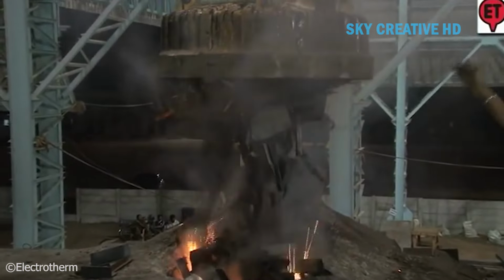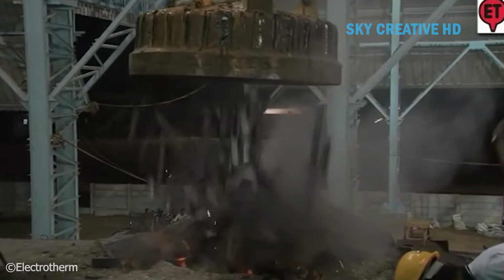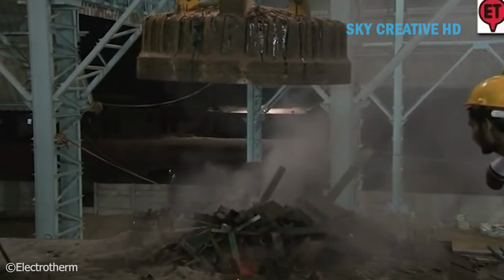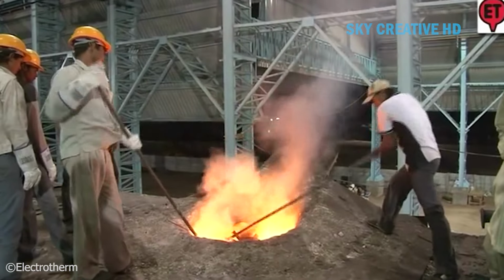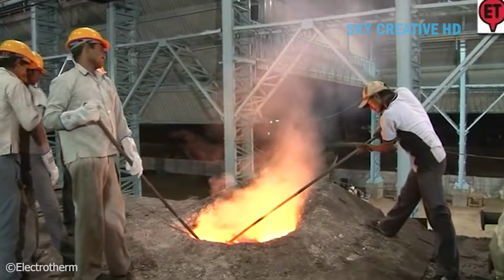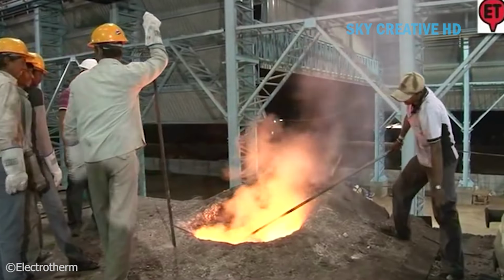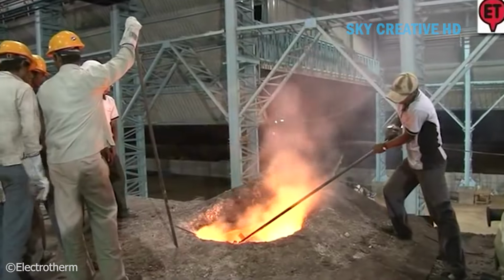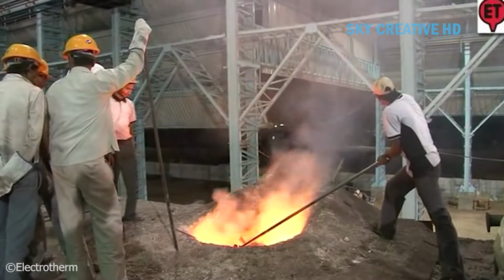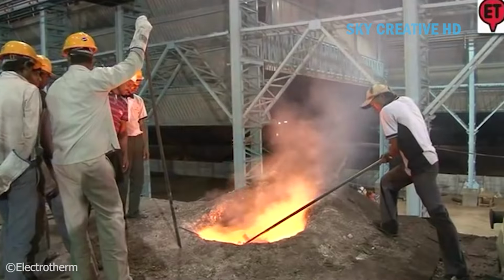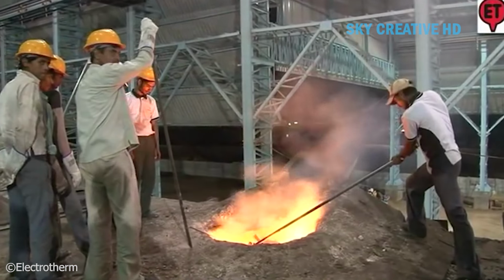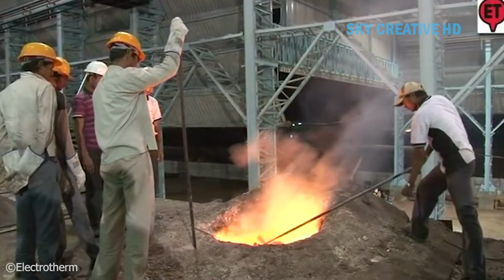The molten steel's composition is carefully adjusted, with alloying elements added and unwanted impurities removed through slag formation. Oxygen sensors and spectrometers continuously monitor the melt, ensuring it meets exact specifications before tapping. Once the steel chemistry is perfect, the furnace tilts and pours its molten contents into a ladle, a massive refractory-lined vessel that can hold 50 to 150 tons of liquid steel.